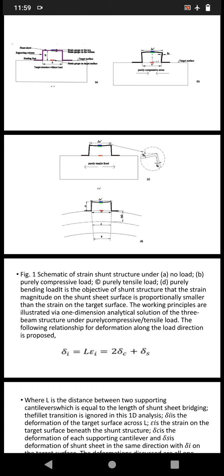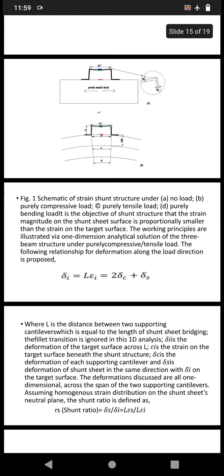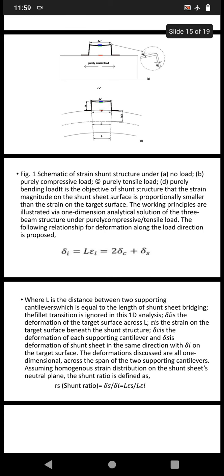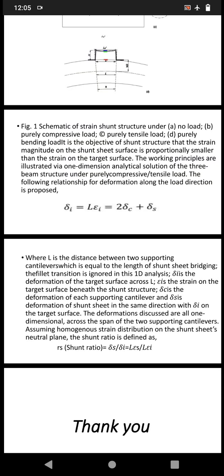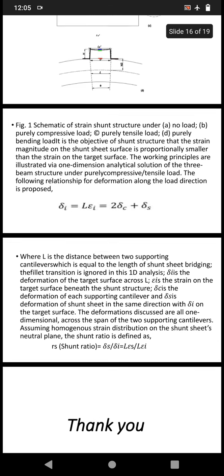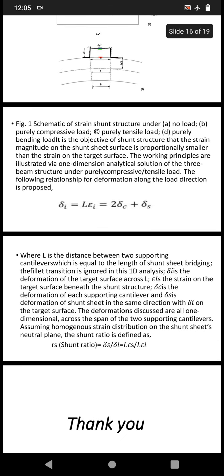The working principles are illustrated via a one-dimensional analytical solution of a three beam structure under purely compressive or tensile load. The following relationship of deformation along the load direction is proposed. Where L is the distance between two supporting cantilevers, which is equal to the length of the shunt sheet bridging the cantilevers. The fillet transition is ignored in this 1D analysis.